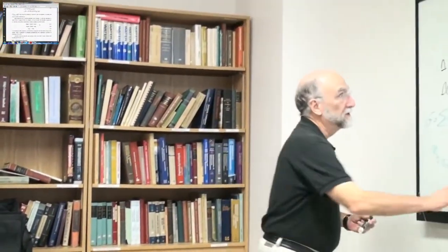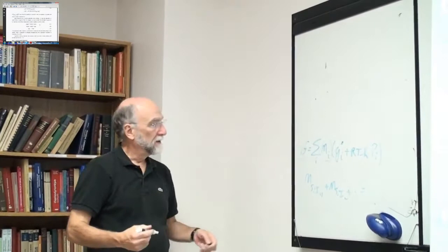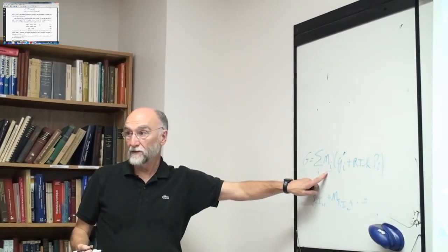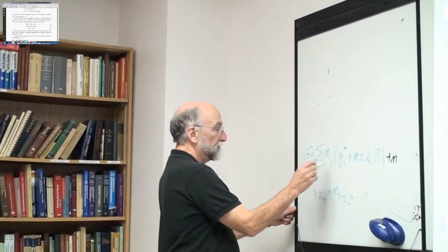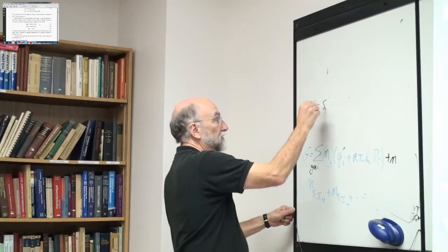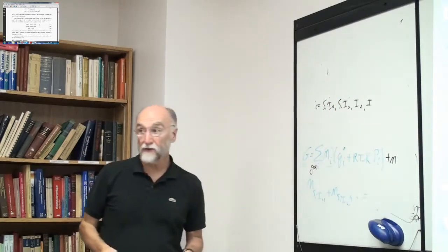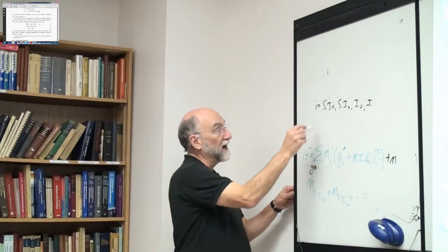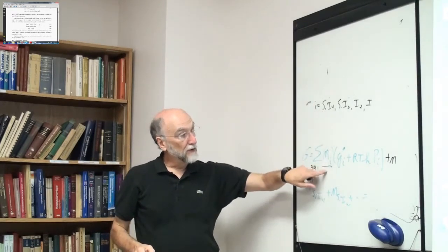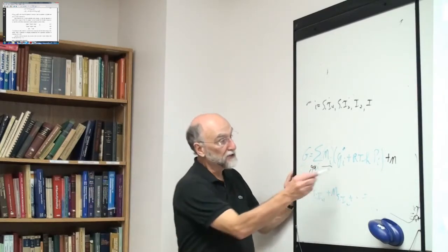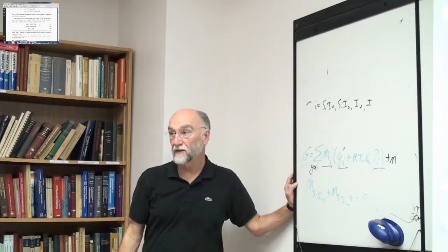Okay, in this example, Ni is the number of moles of each particular species, plus we'd have all the I gas. So the gaseous species are silicon tetraiodide, silicon diiodide, I2, and I. So this is the Gibbs energy, where Ni is the number of moles of that particular gas. So N SiI4 is the number of moles of SiI4 in the system, and so on. G0 is the standard Gibbs energy of silicon tetraiodide, and this is the partial pressure of silicon tetraiodide.